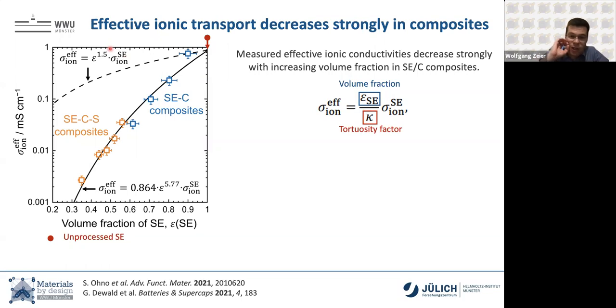By putting these ionic conductors in a multi-phase composite, the ionic conductivity drops over 2 orders of magnitude. 2 orders of magnitude is way too much. For those of you that are familiar with the battery field, there's a so-called Bruggeman relationship that is used to model these tortuous pathways in liquid cells, and this would be this behavior. So in solid electrolytes and solid-state batteries, it's actually worse.